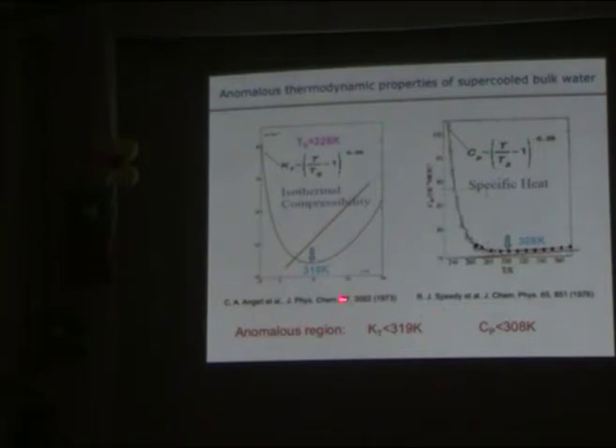This is experimental data going back to the 1970s, done by Angell and by Speedy. As you go down to the lowest temperature that non-confined water can access, which is roughly around 240 Kelvin, this is the lowest data one can access. If you try to fit this data near the lowest temperature, you find some kind of power-law scaling behavior, with a fitting temperature of roughly 228 Kelvin.